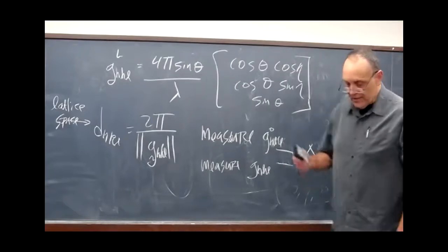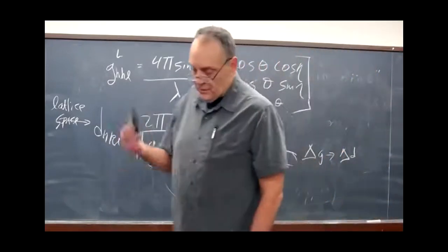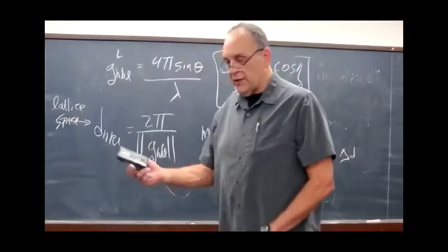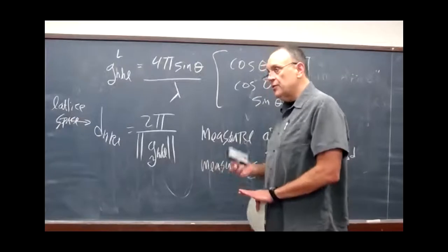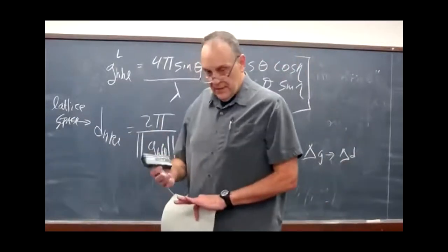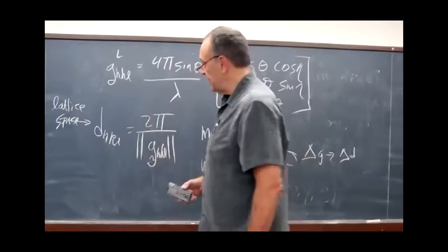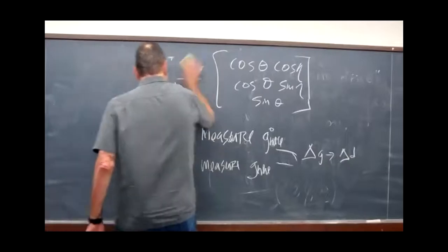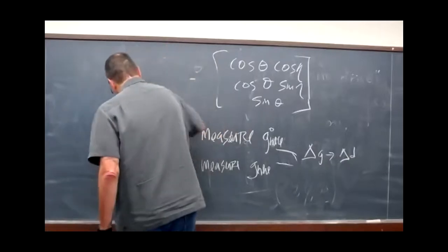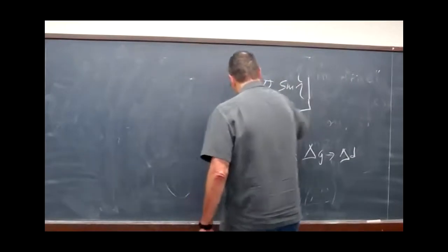So again, the steps. You have 2 theta, eta, and omega for every spot. You watch the spot shift. So now you have an initial G, you have a final G. So literally you'll have a column of G vectors, and you do the delta between before and after. Now this is all in terms of the kinematics here.